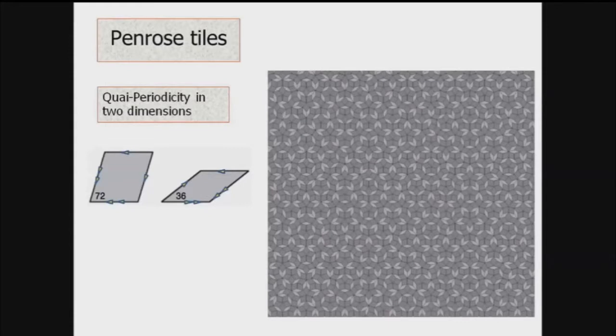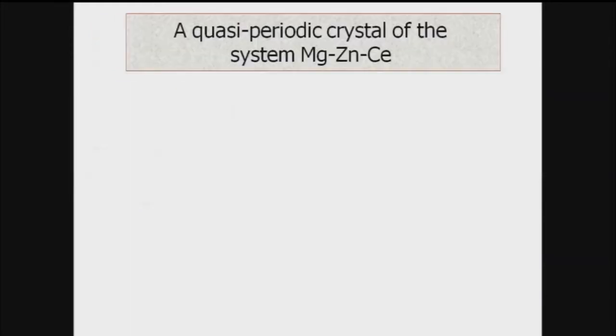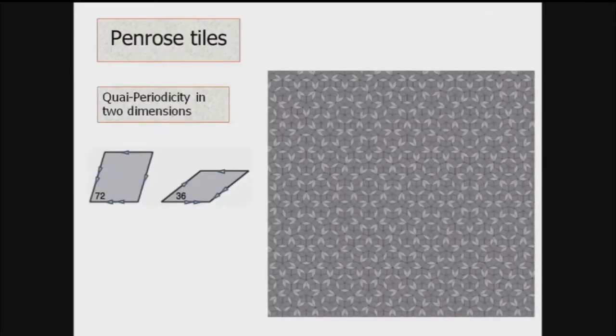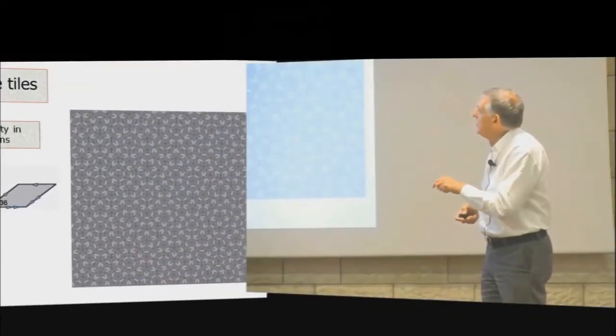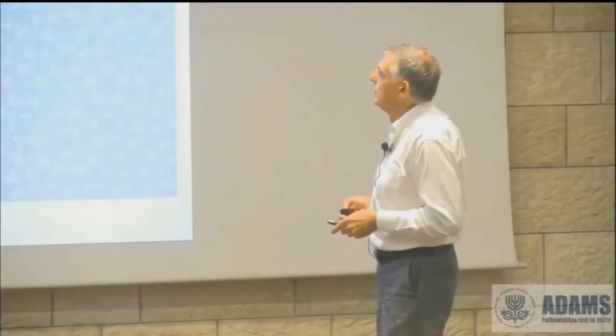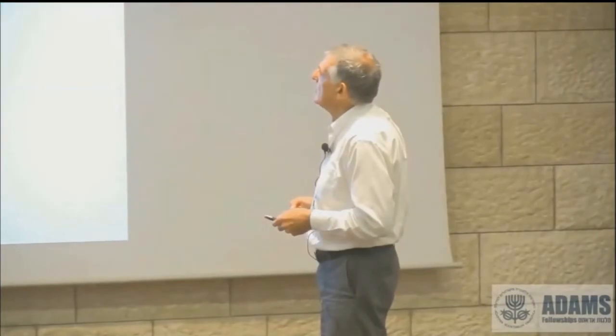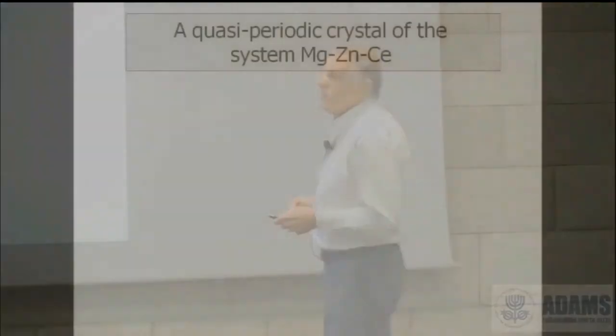What's interesting is that if you take a diffraction pattern from this, you would get something similar to the diffraction pattern that I found in those quasi-periodic crystals. It has five-fold rotation symmetry. This is Roger Penrose. The one who discovered the diffraction pattern, by the way, is Alan Mackay, another British scientist, a crystallographer, who did just that. He took a diffraction pattern of that and showed that it forms five-fold rotation symmetry, sharp spots in the reciprocal space. Okay, so this was two dimensions.